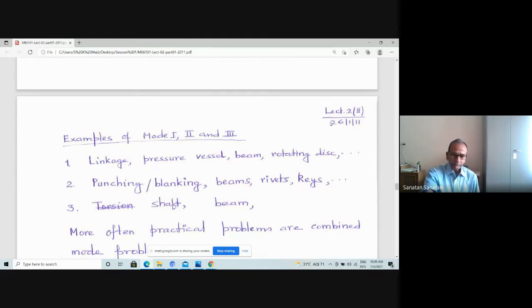Now coming to mode 2: shearing, punching, blanking. When you take a thin sheet and you do the punching operation, when you push the punch, it enters into the material and tries to take a bit of material with it. It goes in the direction of movement, and finally it gets separated from the remaining stock, and that leads to separation. And therefore, you see, this crack which is propagating as the tool moves is a mode 2 crack.